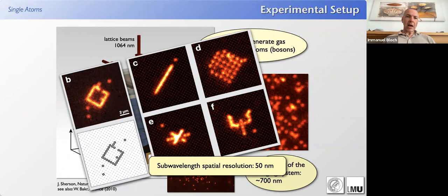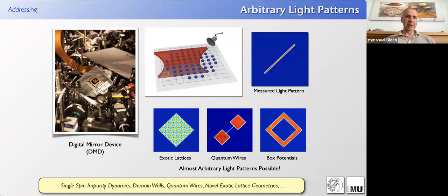Nowadays, we're actually using a different technique to create these optical potentials, which is even more flexible than just interfering different beams from different sides, but we're using these so-called DMDs, which are arrays of micromirrors, which allow us to create almost arbitrary light potentials. We shine a Gaussian laser beam onto this micromirror array, and out comes the basically target pattern of light that we want. So for example, we can have a line of light, we could have more exotic lattices, we could have two reservoirs, two boxes, where we fill one box with atoms, for example, and study the transport of atoms from one box through this wire of light into the second box. So you can study conductance through these thin wires of light.